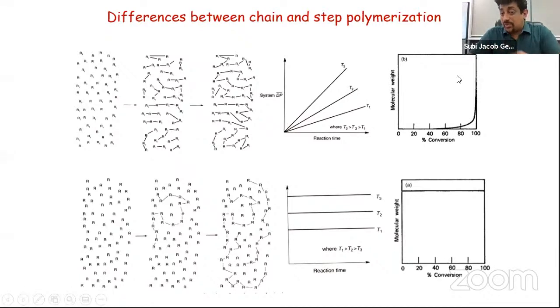And obviously, dispersity control is better here in condensation polymerization. But when it comes to chain growth polymerization, we know that we don't have perfect control on the dispersity, but we can get high molecular weight at any stage of the polymerization reaction. This is very important, because if you start making a supramolecular polymer and you are not able to get high molecular weight, that probably means you should know the mechanism. Unless we have a clear understanding of the mechanism, we may not have this structural control.